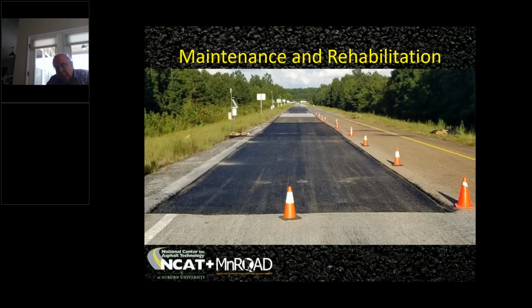Of course, maintenance and rehabilitation is farther down that pavement life cycle curve. So we've done other work on the track with interlayers to determine how an open graded interlayer compares to a chip seal interlayer and to a dense graded, rich pavement interlayer. We've got another experiment on the track right now that a lot of people are interested in, because there are 6 different sections: 2 plant mix, 2 chip seal, and 2 geosynthetics. The plant mix nearest to you is an open graded interlayer. The darker one down past it is an Arizona rubber, highly crack resistant interlayer.